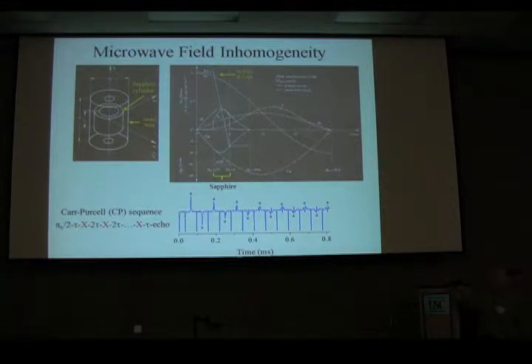So for example this Carr Purcell sequence. Remember there is a CP and also the CPMG. The only difference is for the CPMG you change all those X's to Y's. Naively you would say those sound really a lot alike. But this shows what happens if you keep everything as X's. Here are a series of pulses. So what you can see these spikes going down here are the microwave pulses. It's a little bit of feed through. The ones marked with a star are spin echoes. So between every pair of microwave pulses you get a spin echo. You see this thing decays away to almost nothing in 15 pulses or something like that. So you can't do a lot of pulses here.